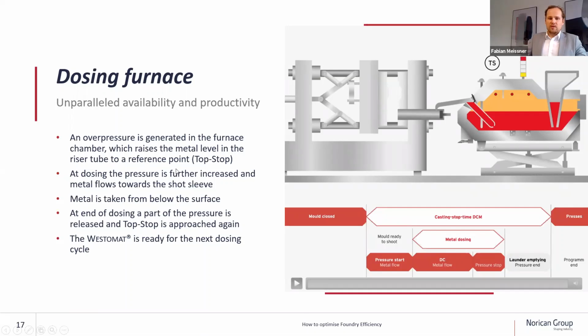We are working with an overpressure that is generated in the furnace chamber, and with this overpressure, we are raising the metal in the riser tube, which you can see here, to a top stop position. So a top stop position is basically that the metal in the riser tube is above the level of the bath in the furnace. So let me show you the animation.